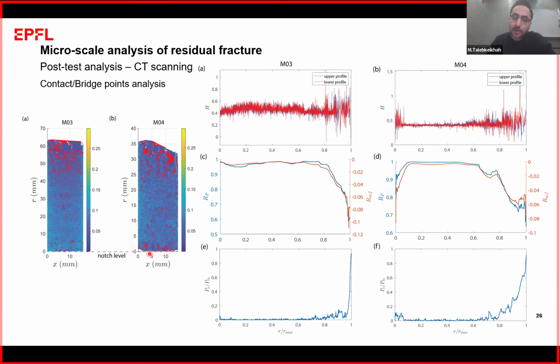So if we count the number of these red points along the location of each row, we reach these two figures here. We could see that exactly at a specific distance from the inlet of the fracture, about 0.7, there is a point where the density of these red points suddenly increases, which we associated with the process zone.